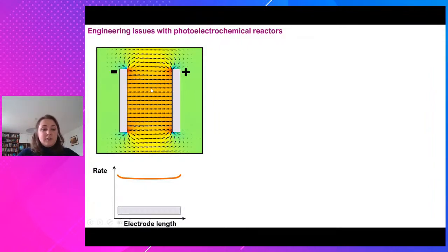Now, the ions in the solution which complete this electronic flow circuit also flow uniformly between the two electrodes to maintain the reaction, which means that whatever reactant is being consumed at an electrode is replenished all the way along the electrode surface, and it's uniform. And so the rate of the reaction is not being limited by non-uniformity of this field. I've shown in a schematic way that the rate of the reactions is uniform along the electrode length, except at the edges where you have some concentrations of the electric field lines.